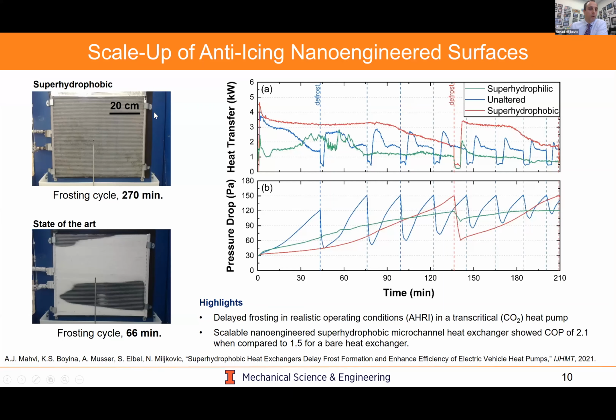This is our super hydrophobic coated microchannel aluminum heat exchanger. This is our uncoated heat exchanger. And what you see is if you plot the heat transfer and pressure drop after integration in a transcritical CO2 heat pump cycle, you clearly see the advantage of super hydrophobic coatings compared to bare surfaces or even super hydrophilic nanoengineered coatings. Similar with pressure drop. And so what this translates to after rigorous quantification is that the COP we obtain with our coated surfaces is 2.1 when compared to 1.5 for a bare heat exchanger that can't delay frosting.